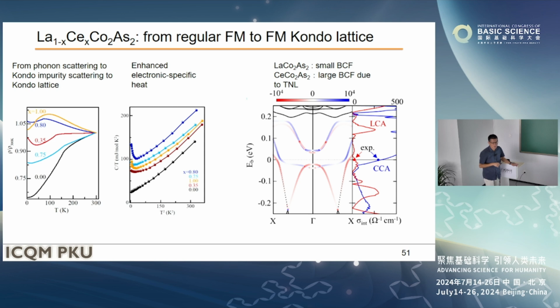Here, for cerium, you see the resistance has log T behavior, which is a signature of the Kondo lattice, and it drops down when it starts to become coherent below the coherence temperature. Okay. Also, we have an enhanced electron specific heat with the increasing of the field, and we also asked the collaborator to calculate the Berry curvature field for the lanthanum and cerium compounds. This is consistent with the experimental result.